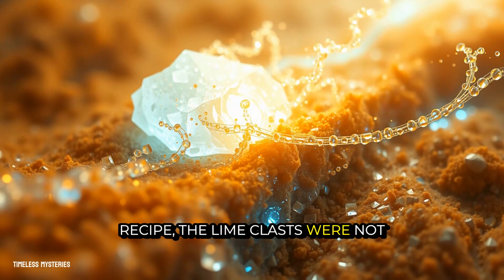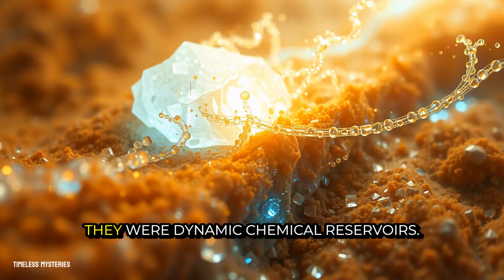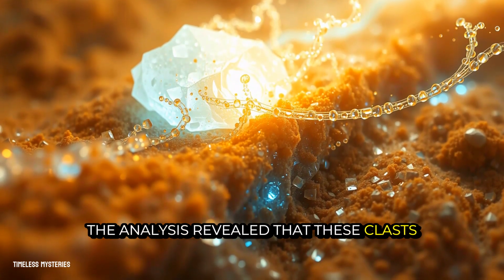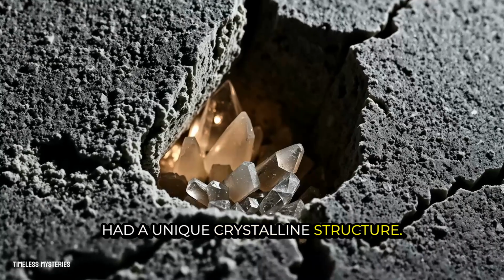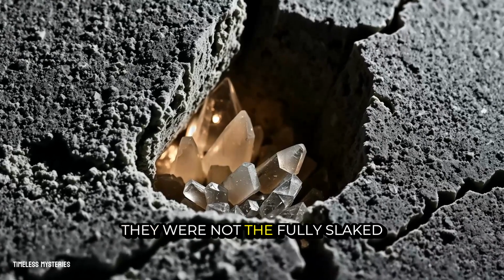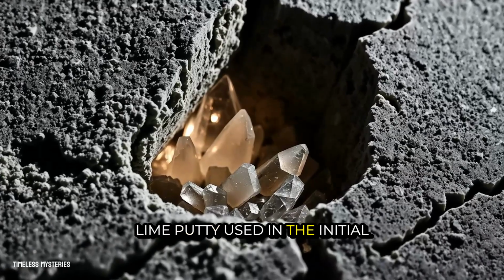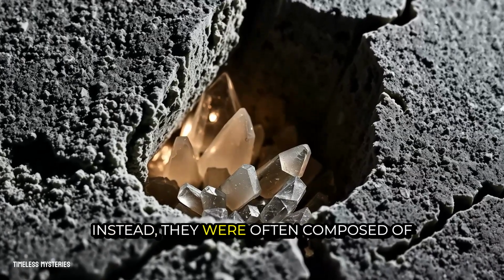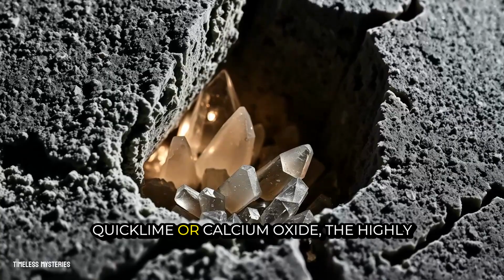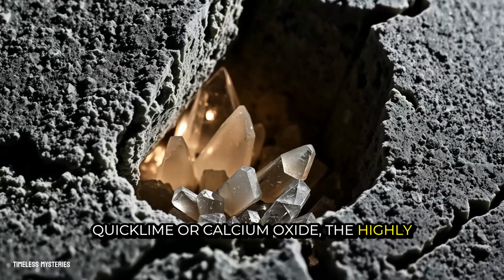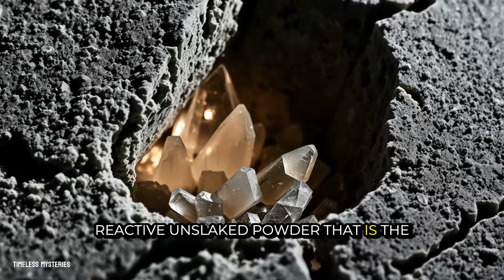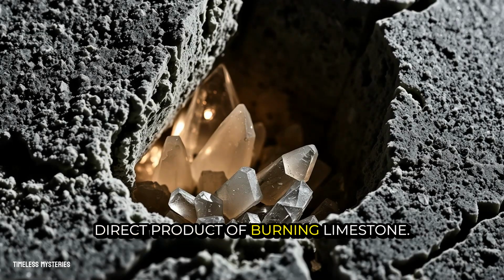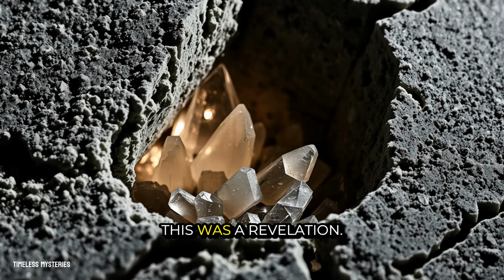The lime clasts were not inert lumps, they were dynamic chemical reservoirs. The analysis revealed that these clasts had a unique crystalline structure. They were not the fully slaked lime putty used in the initial mix. Instead, they were often composed of quicklime, or calcium oxide, the highly reactive, unslaked powder that is the direct product of burning limestone. This was a revelation.